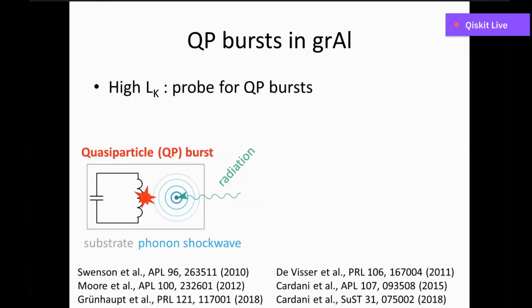As I mentioned previously, radiation will affect our circuits by breaking Cooper pairs in them. And this is mediated by phonon transmission in the substrate. What happens is that once phonons generated in the substrate reach the superconducting circuit, if their energy is sufficient, they will break Cooper pairs, decrease the Cooper pair density, and increase the kinetic inductance.